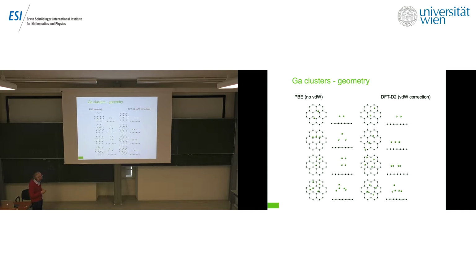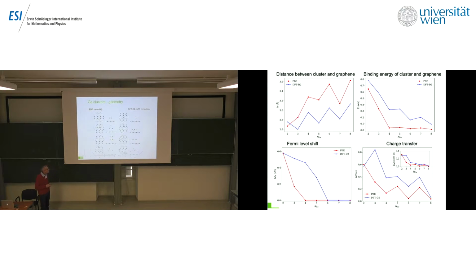But this is not the case if you have van der Waals interaction there; it still remains in one plane. And then we continue, there are four atoms, there are two atoms above that in the equilibrium state, and here it is still in one plane. And only after we put there five atoms, even with the van der Waals forces, does it seem to make clusters.